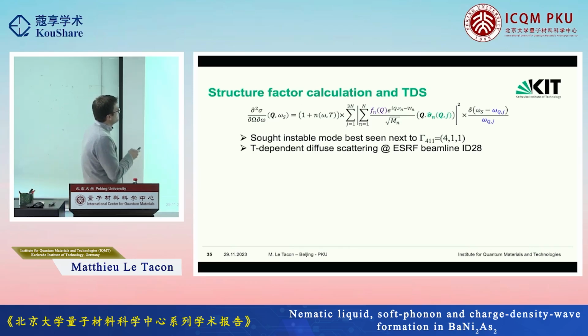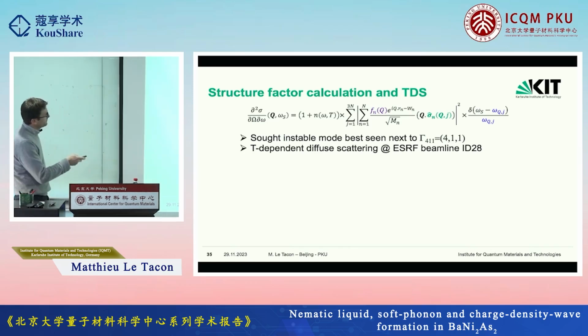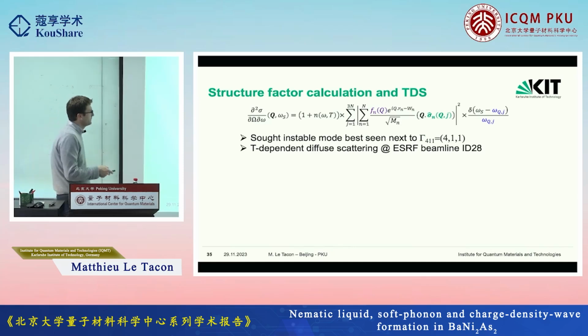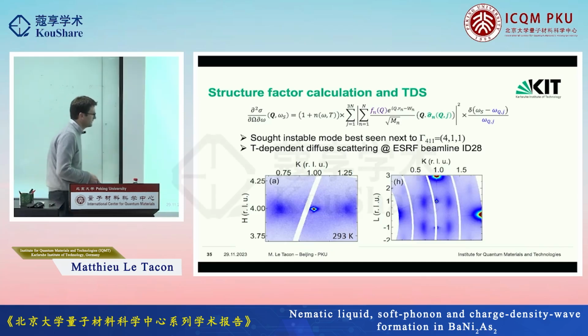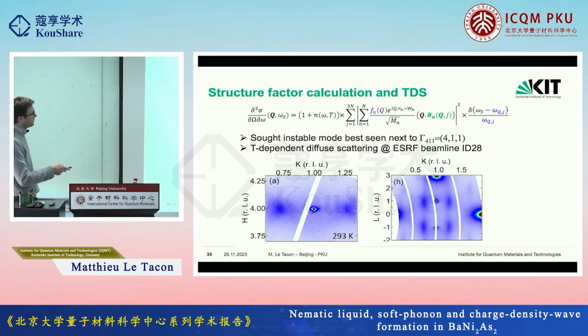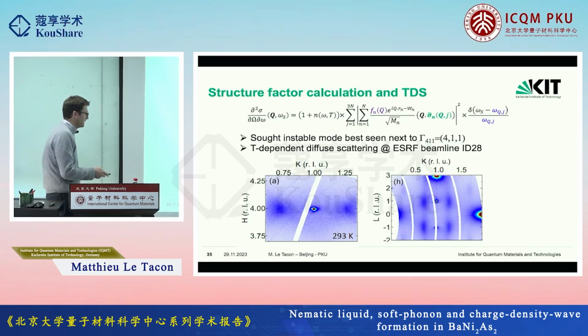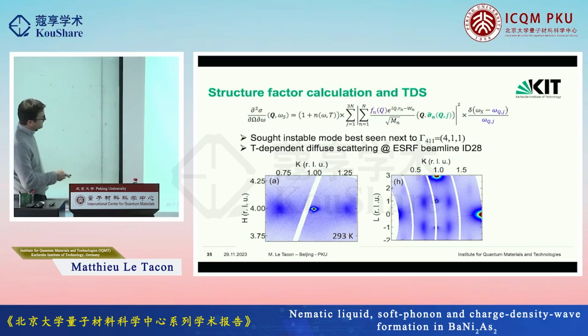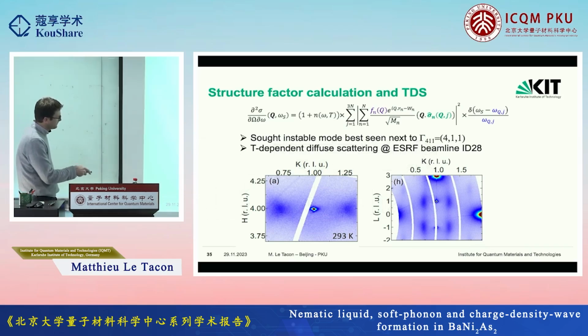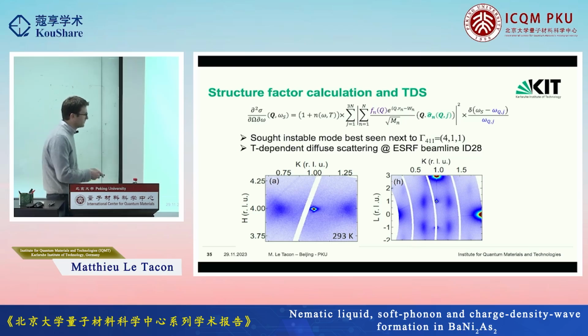phonons. We can also calculate the structure factor, of course, for the phonon in the calculation, and we did some temperature dependence in elastic scattering around the 411 Bragg reflection. That's where we thought we had the biggest chance. So what we see here is basically the 411 Bragg reflection, and you can see that around it you have this nice diffuse satellite. So there's no way you can see that in the lab.